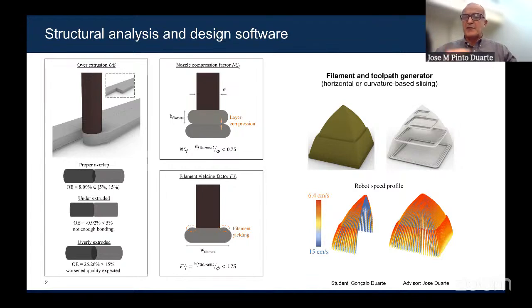Because, for instance, in this case, if you start printing from the bottom, the layers harden, and then when you go to the top, the bottom layers are hard, but the other ones are in intermediate stages of hardness. So you need to understand if the structure is strong enough to avoid collapse during printing. So one thing we need is an element of the system to predict the shape of the filament. You need to make sure the filaments have good bonding, both in terms of vertical bonding and horizontal bonding as well.